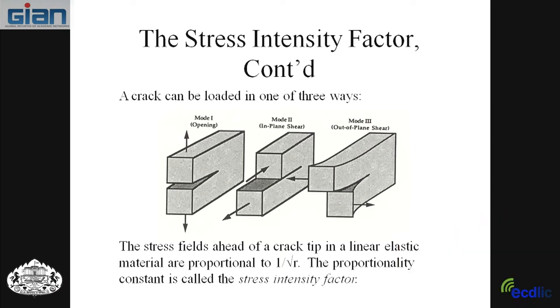One is opening mode, and opening mode has all the loads and stresses perpendicular to the crack. Mode two is in plane shear. The loads are parallel to the crack, loads and stresses, but they are in the plane. And mode three is out of plane shear. The stresses and loads again are parallel to the crack, but they're out of the plane, tearing the thing. This is what people used to use in the old days when they wanted to tear up the New York City phone directory. I don't know why they wanted to do that, but some people did. So you use a mode three approach. 90% of what we talk about in fracture mechanics is mode one, opening mode. Seems to be the most damaging.